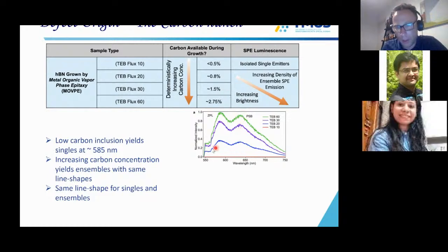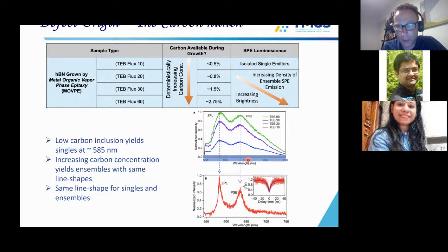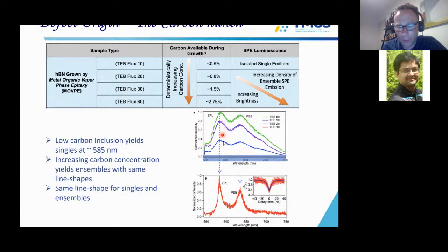And so then when you get to this 0.5%, you can employ a confocal microscope and basically reproduce this very nice zero phonon line with a phonon sideband and measure an anti-bunching curve. When you study new quantum systems or new optical defects, it's very important to actually resemble the optical features of a single defect with an ensemble, like in the case of the NV center in diamond. And so this is a very strong evidence that we have a carbon influence in our defect.